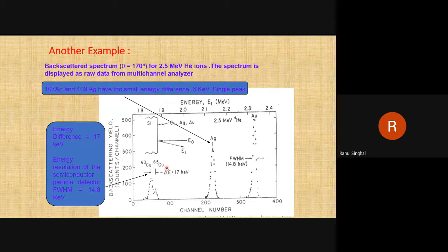Okay, so it depends on the mass of the element. Here, like silver, we have the two isotopes. For both silver isotopes, the mass is the same, and for the copper, the mass is the same. But copper and silver, their mass itself is different. So because it depends on the backscattered energy, once helium ions come and hit your silver or copper, they will lose different energy. After losing the energy from copper 63 and copper 65, the energy difference is 17 keV, which is bigger than the resolution of our detector. So we are getting two peaks.